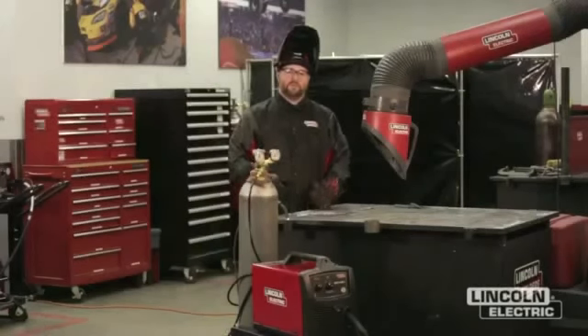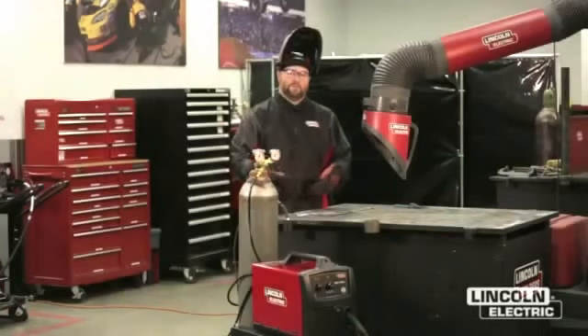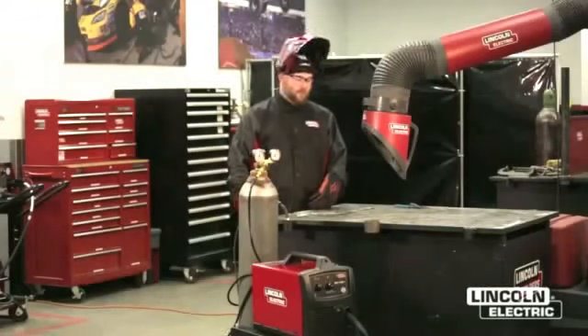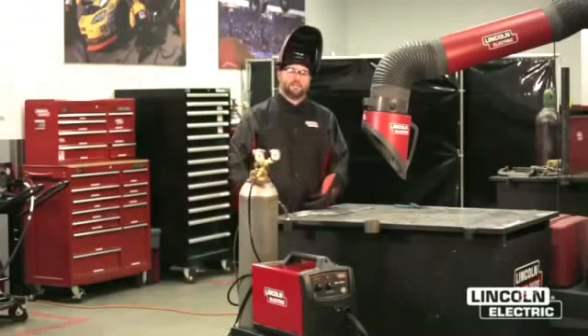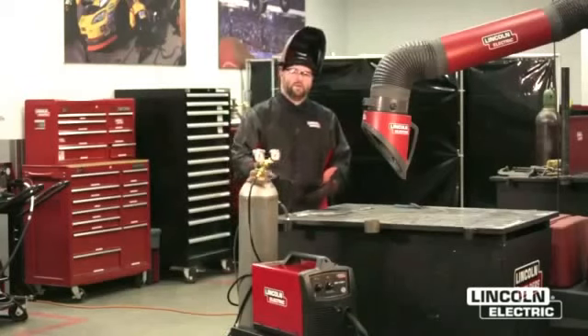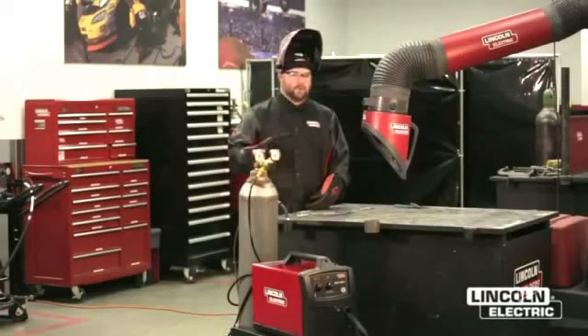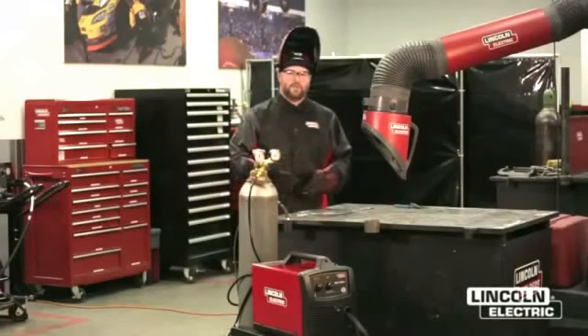We covered wire feed speed. We covered our travel speed being too high or too slow. And we also covered the effects of our contact tip to work distance and all the effects of our angles, our work angle and our travel angle. So just again, read that puddle. That's going to tell you what you need to adjust.